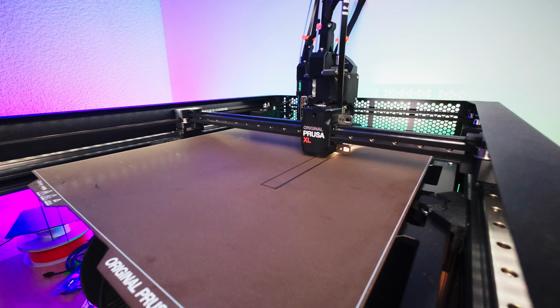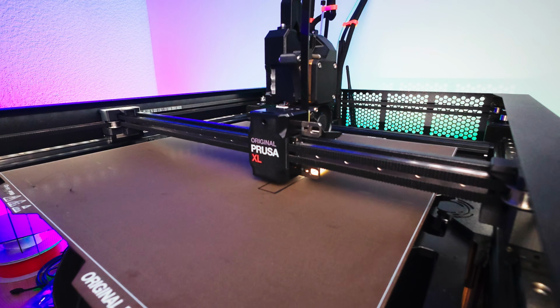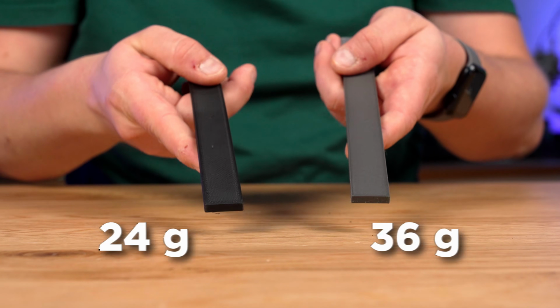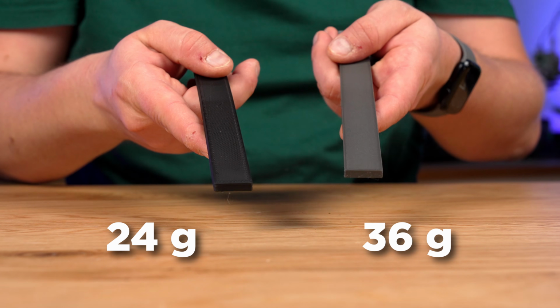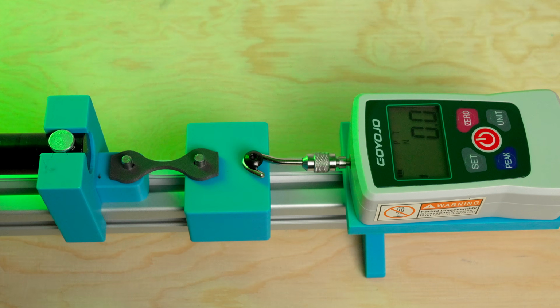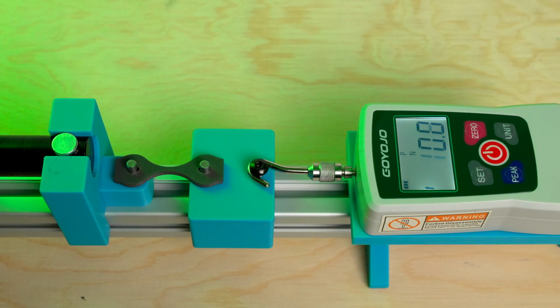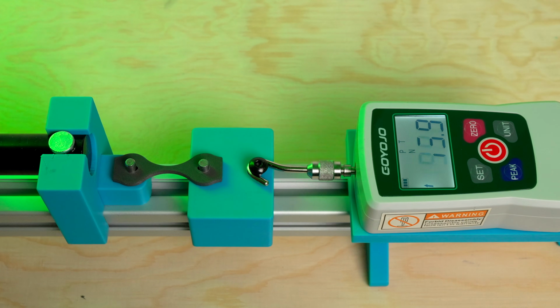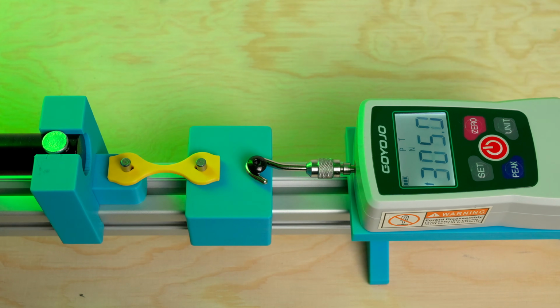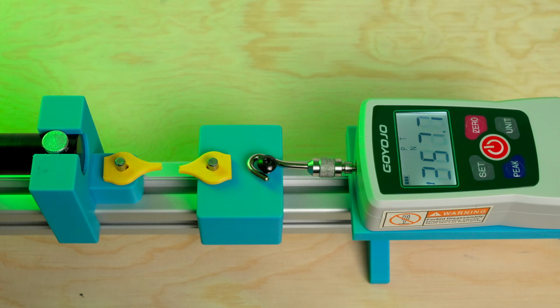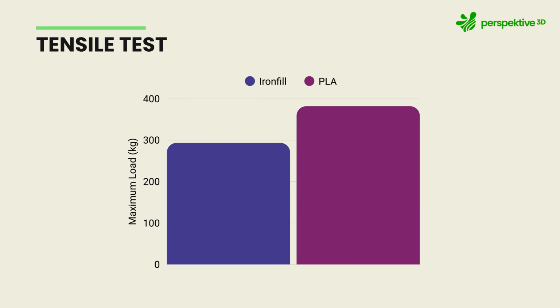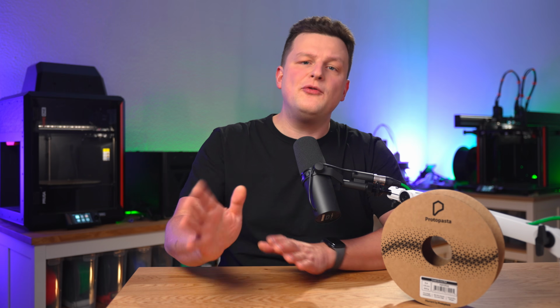With everything set up, I started my first print, and the moment I pulled it off the build plate, I immediately felt the weight difference compared to the same print in regular PLA. And that made me wonder, with the added metal, is it actually stronger, or does the extra weight hide a weakness? To get a clear answer, I ran a tensile test on my new tensile test machine. No guessing, no assumptions, just controlled force to see how the material really behaves. And compared to standard PLA, the result was obvious. Iron-fill is weaker. And the reason is simple.